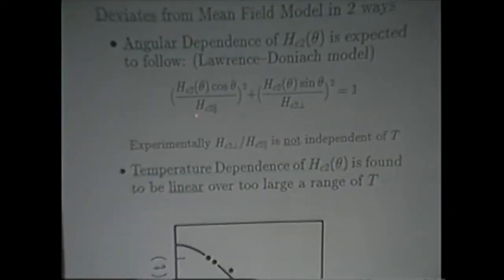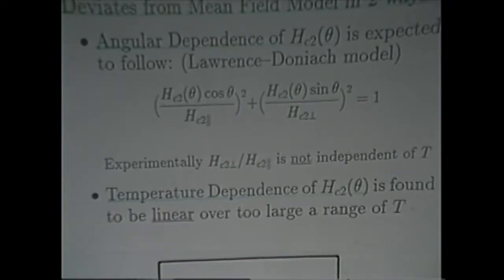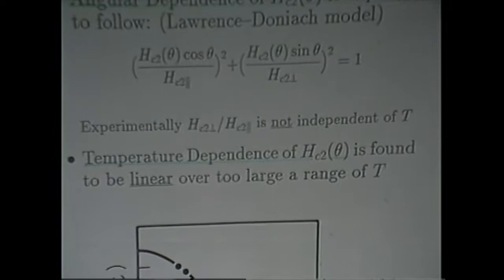However, there are things about it that are unexpected. This is an anisotropic system, and you're quite prepared that the critical field will be anisotropic. It should be. And there's a theory for anisotropy in critical field, a mean field theory, and it gives a prediction for the angular dependence of the critical field in terms of a parameter, HC2 parallel for theta equals 0 when the field is along the c-axis, and HC2 perpendicular when it's at right angles. And the problem is that in the intercalation compounds, the ratio of these quantities, HC2 perpendicular to parallel, is not independent of temperature.